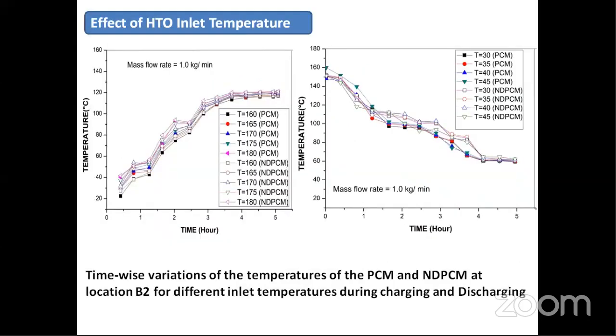The next slide, effect of heat transfer oil inlet temperature. The melting time was reduced by 19% for pure PCM and about 21% for NDPCM when the heat transfer oil inlet temperature was increased from 160 degrees Celsius to 180 degrees Celsius. The solidification time was reduced by 10% for PCM and 14% for NDPCM when the heat transfer oil temperature was decreased from 45 degrees Celsius to 30 degrees Celsius.